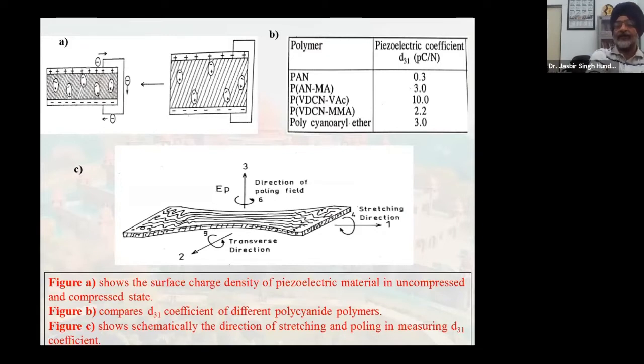The material which I worked on initially had 1 picocoulomb per newton, but with the help of stretching and corona poling, we were able to increase it to around 4.5 or 5 picocoulomb per newton. So we increased the value by 5 times. That was the improvement. Otherwise, PAN methacrylate, polyacrylonitrile methacrylate, has a piezoelectric coefficient of 3, and this has 2.2. Polycyanoaryl ether again has a D31 of 3 picocoulomb per newton.